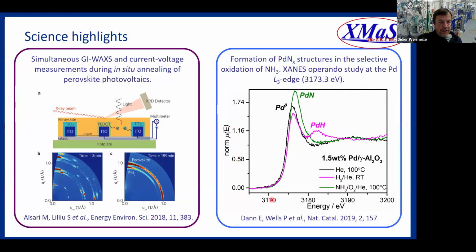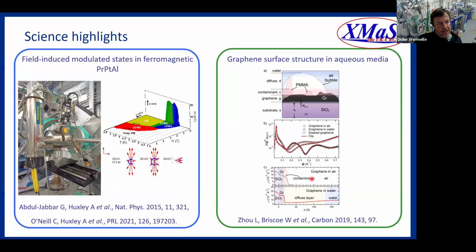This is an example in the tender X-ray regime here at 3.1 keV. This is the Palladium L3 edge for an operando experiment on measuring the XANES on the sample. And then here on the left, I mean, what used to be the core type experiments of XMaS.